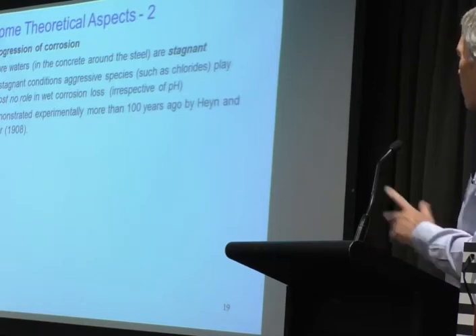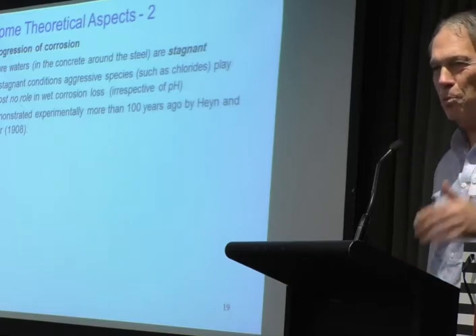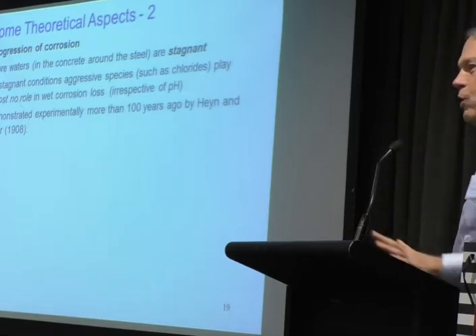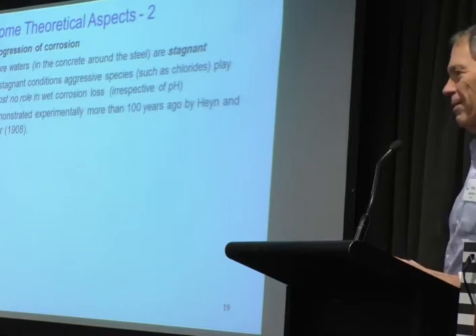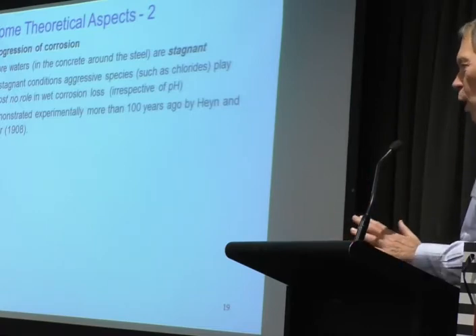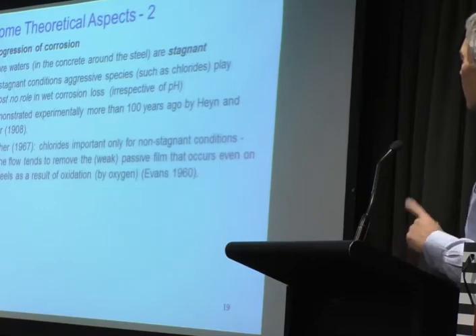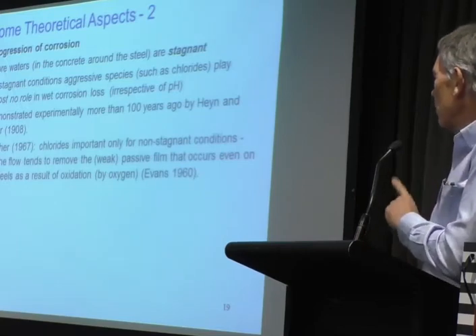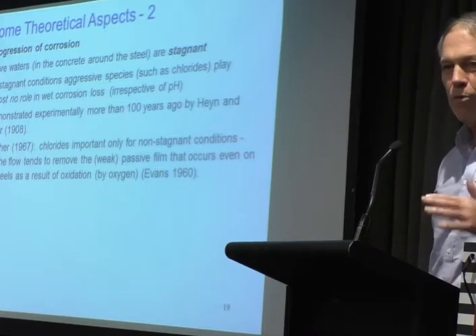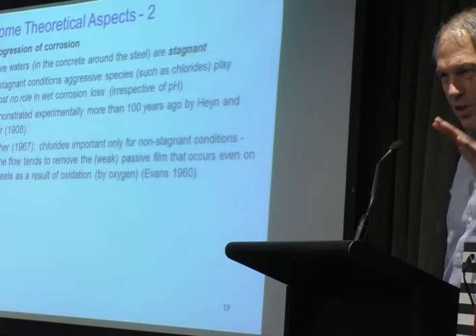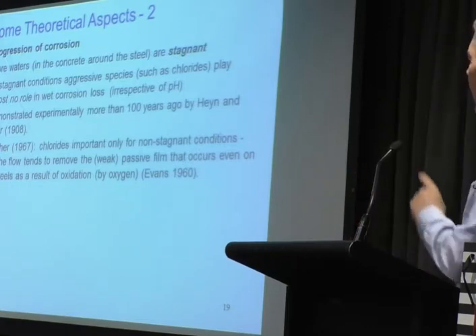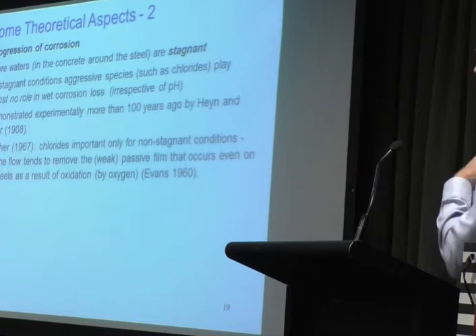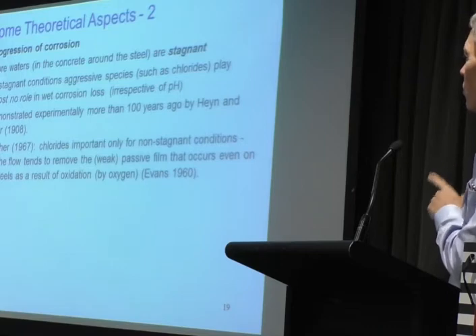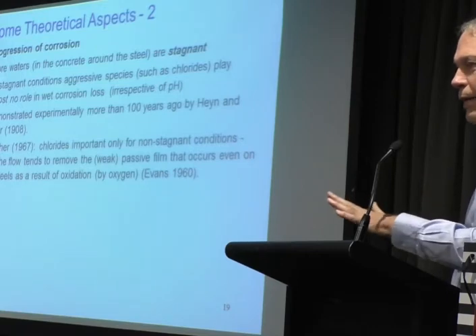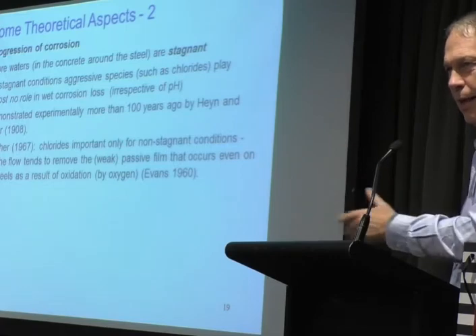And that was shown more than 100 years ago by these two guys in Germany, and it's a nice German paper, you can have fun reading it, and they look at lots and lots of salts, made almost no difference, provided it was stagnant. And why is that? Well, if you go and read Evans's book, even things like carbon steels form a very weak passive layer, right? And he showed that. You can read his book, how he did that. And Dora Brasher in 1967 threw some light on this and said the chlorides are only important in non-stagnant conditions, because then you actually damage that oxide layer.